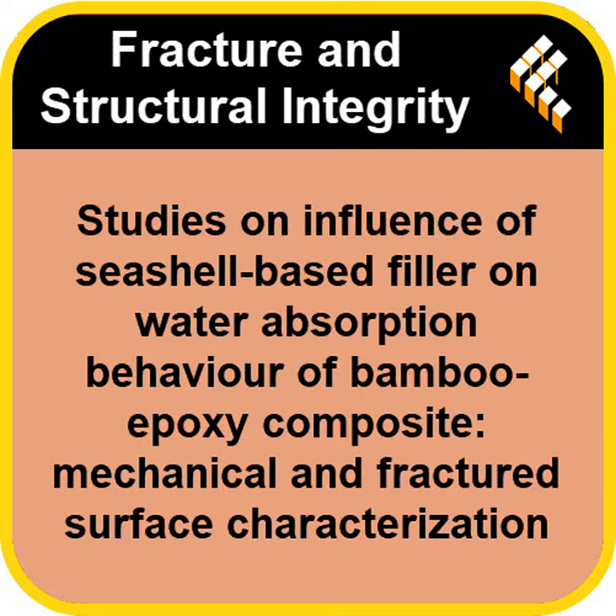As soon as they added the clamshell powder, water uptake dropped. But here's the interesting part. There was a definite sweet spot. More wasn't just better? No. The sample with 6 weight percent clamshell filler showed the lowest water uptake, only 4.07%. How much better is that compared to the control? That's a 30.4% reduction in water uptake, just by adding 6% of this waste powder.